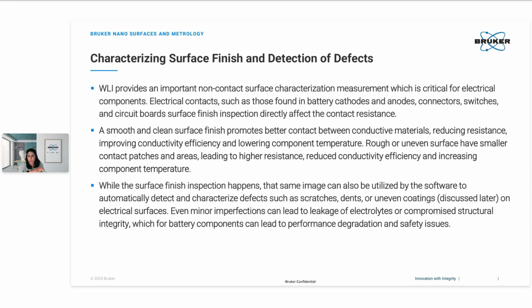And here WLI, white light interferometry, can provide you a high-accuracy, non-contact method to validate your surfaces without any impact by the measurement itself. A further advantage of this technology and method is that by using the same 3D image of the surface we are measuring, you can also detect and characterize defects, and not only do one measurement per image.